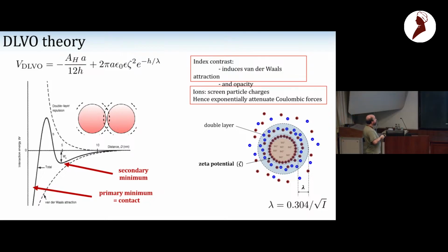So the interactions between our particles are controlled by the DLVO potentials. So you have van der Waals attractions, you have the repulsion, which is due to the charges. This repulsion is screened, and when you have ions, you strongly screen the Coulombic. So these particles are charged, right? Silica in water is charged, so they repel each other. But if you have an ionic suspension, and that's really very general in nature, you have many mineral suspensions in which you have ions.